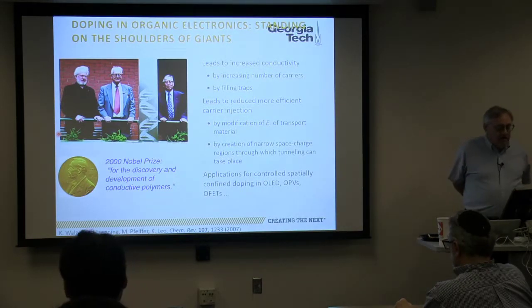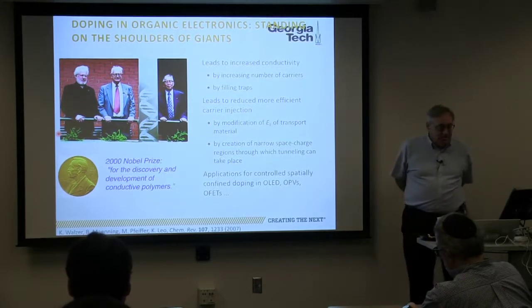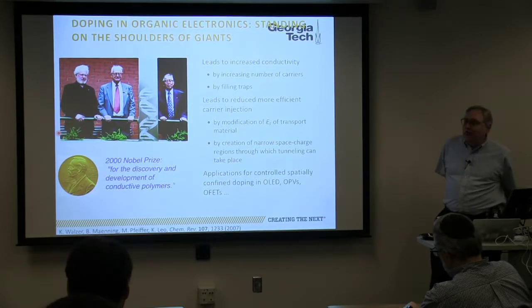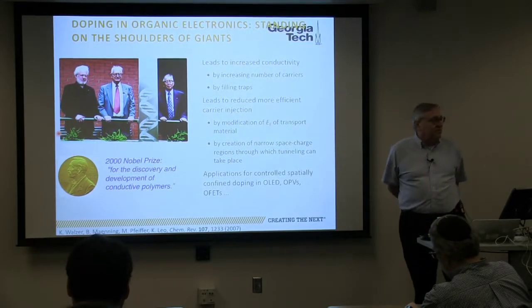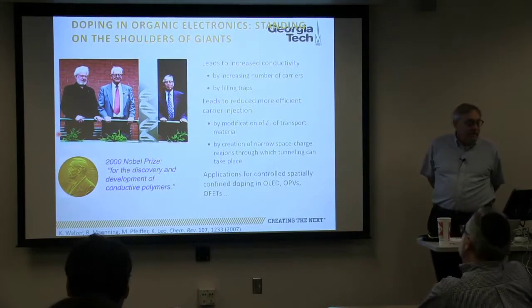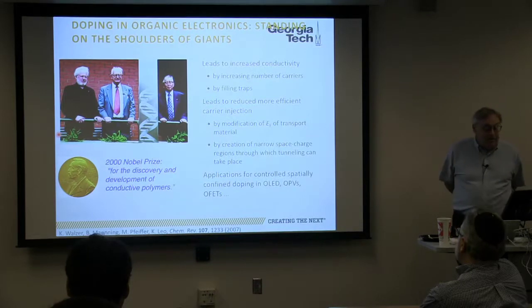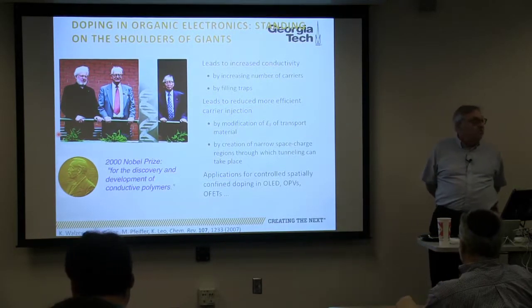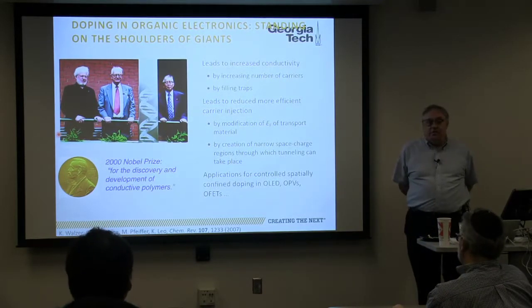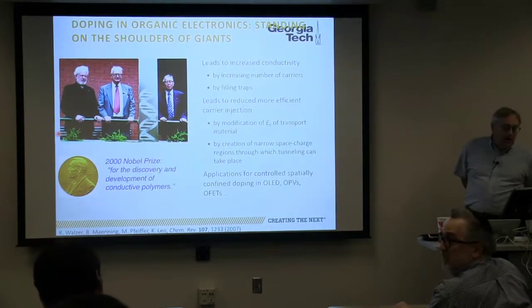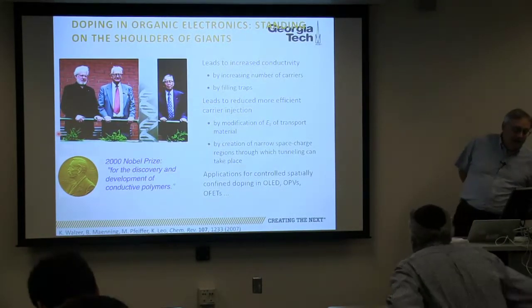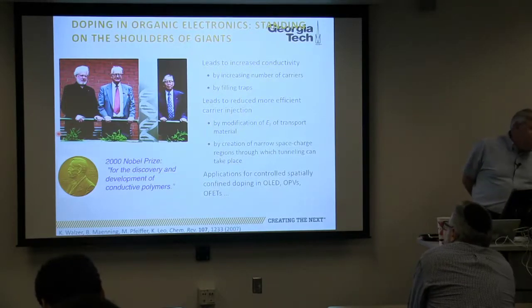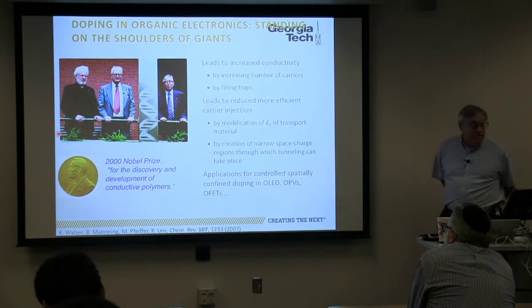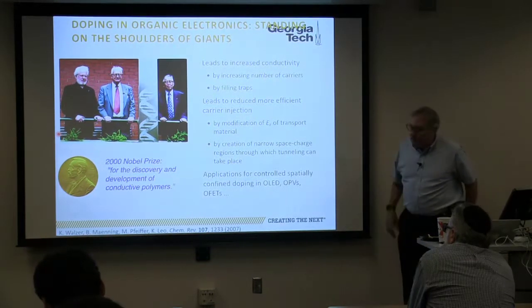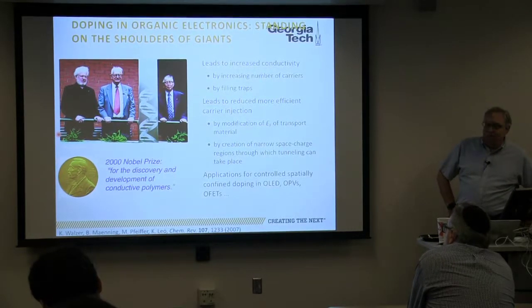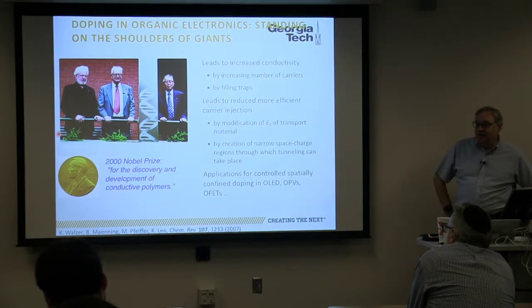And so it turns out that like other semiconductors, and I'll go into this in a little more detail, you can dope them. But the whole concept of doping in organic semiconductors is somewhat different than inorganic materials. And when you dope them, you can increase their conductivity by injecting carriers. You can inject both electrons and holes. You can fill traps that improve the mobility. You can also have doping near interfaces with electrodes that can lead to either more efficient charge injection into the material or charge collection from the material if it's a solar cell. And I have a couple of bullets for how that's done. And as I said, these have found applications in OLEDs, OPVs, OFETs, and other applications.